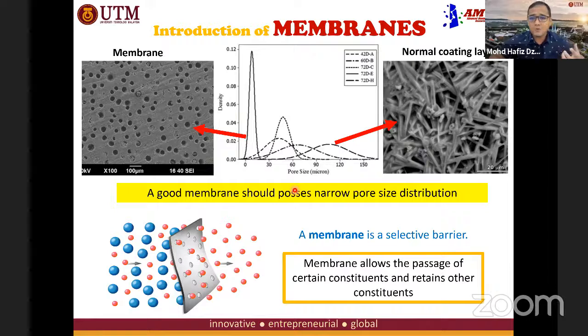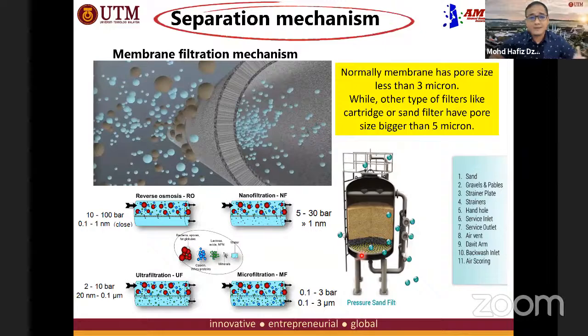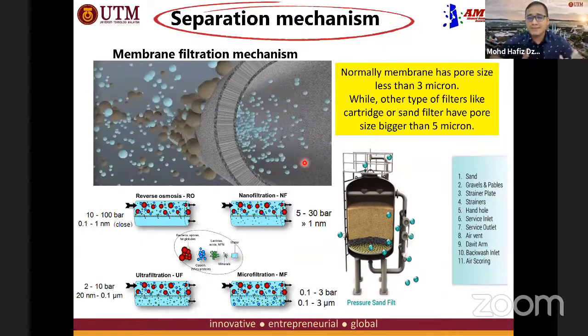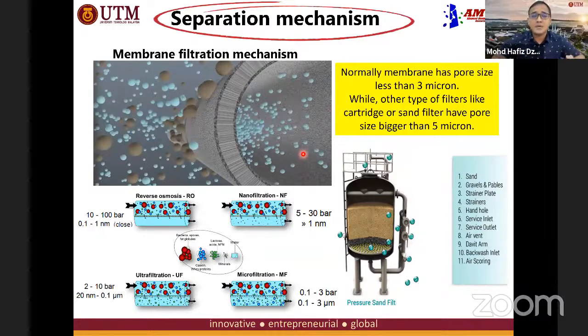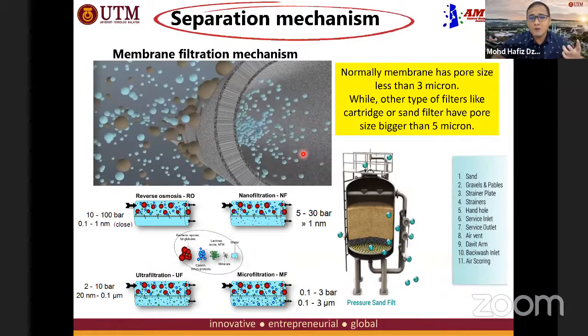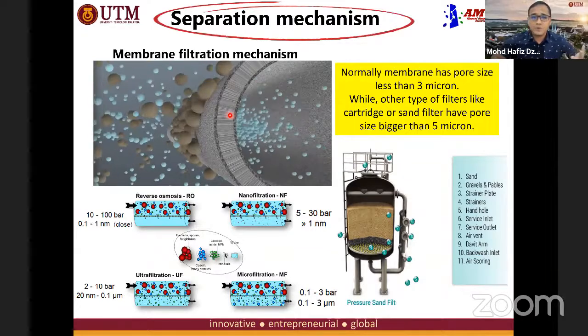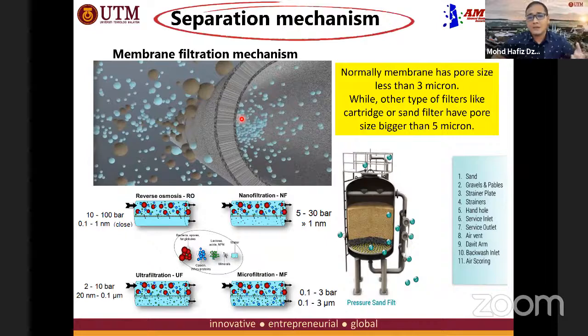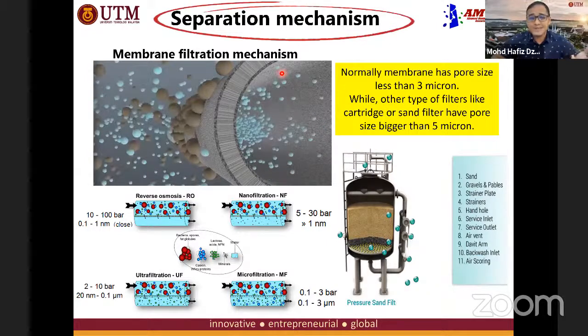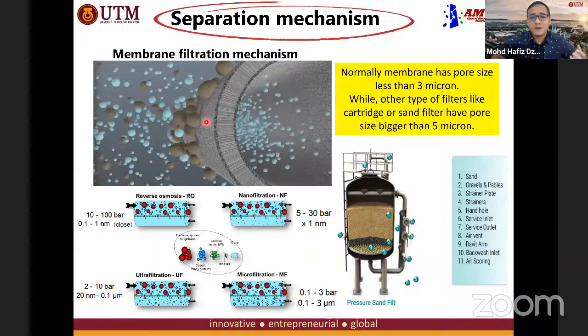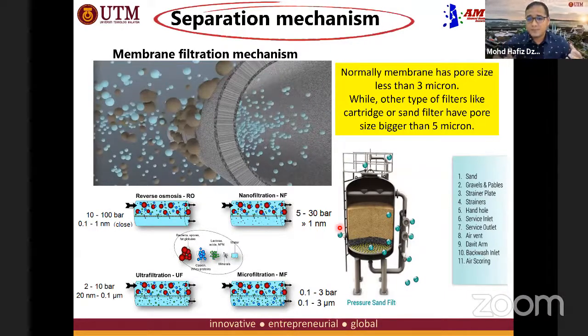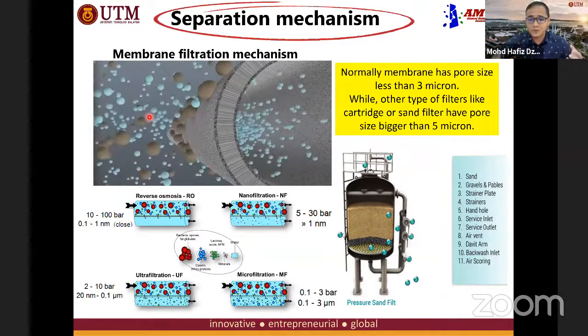Due to its narrow pore size distribution, membrane acts as a selective barrier, meaning that it only allows certain constituents to pass through and retains the other constituents. So the concept of a membrane is quite straightforward. This is the conventional mechanism of membrane, based on filtration. The membrane allows small molecules smaller than its pore size to pass through on the permeate side, and retains the bigger molecules on the retentate side. Therefore, the pore size of the membrane is really important to make it very selective in order to increase the separation efficiency.